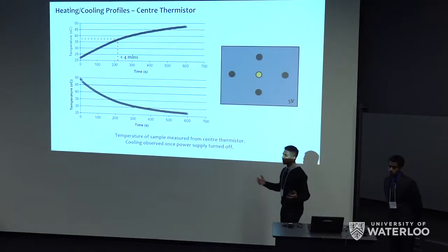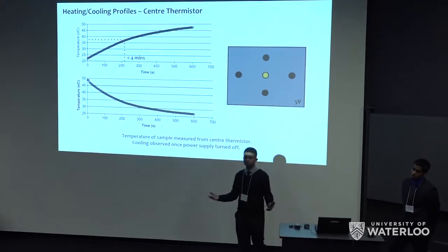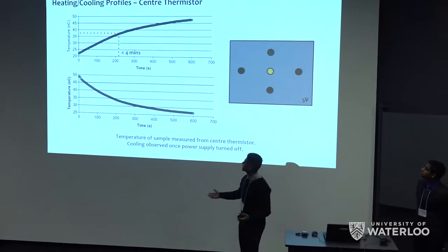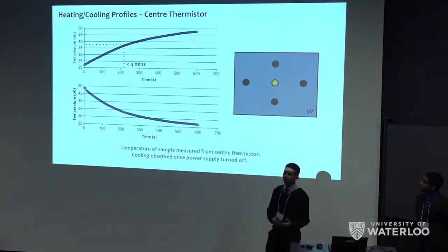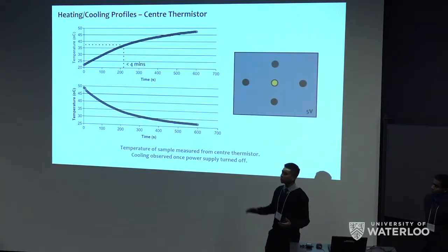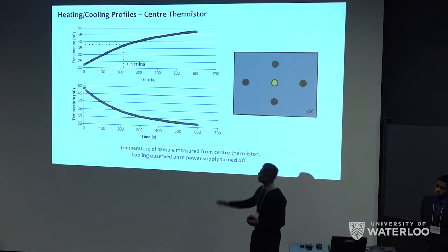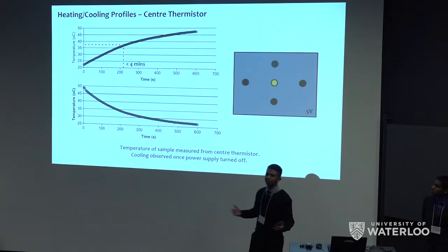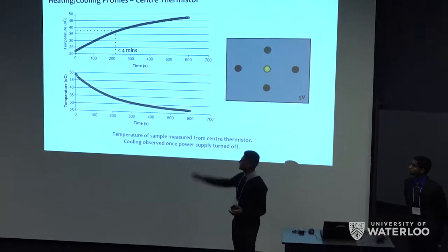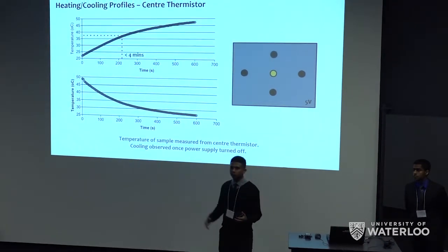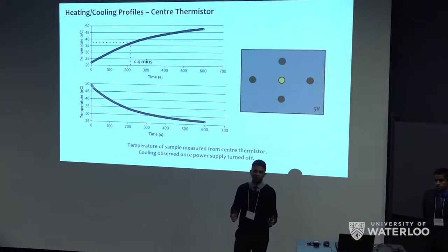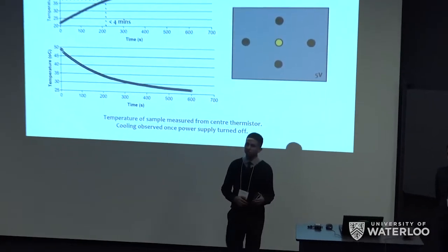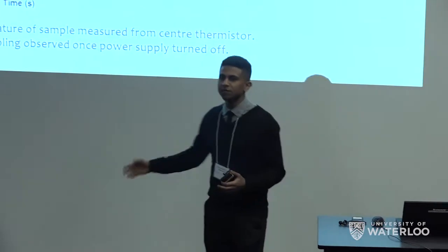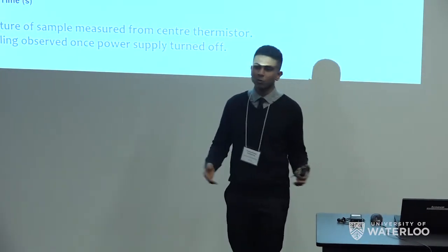And obviously, our huge concern was heating and cooling profiles. So what we have here is a heating profile where we're supplying about 1.5 amps of current through our material. And we're just exploring how long it takes to achieve certain set temperatures. So we can see that within 4 minutes, we already hit the desired 37 degrees Celsius that we had in our customer requirements, which is pretty impressive. And as we continue, we can hit upwards of 50 degrees, which is well beyond what we require for applications in apparel.